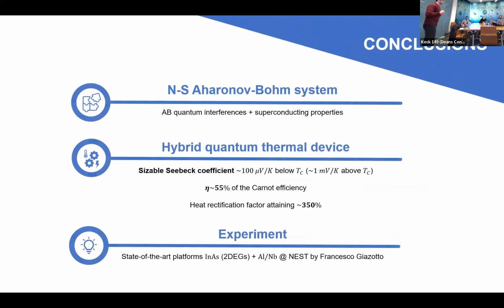Let me just go rapidly through the conclusions. In this presentation, I talked about this hybrid normal-superconducting Aharonov-Bohm system, and I hope I convinced you that by putting together the physics of the interference mechanism of the Aharonov-Bohm system with the superconducting property of the superconducting lead, you can really realize a multitasking and versatile quantum thermal system, which exhibits a very high and sizable Seebeck coefficient in the linear response regime, also very high efficiency in the nonlinear response regime, of the order of 55%, and this system can also be used as a heat rectifier, attaining 350% of rectification in the optimal case.